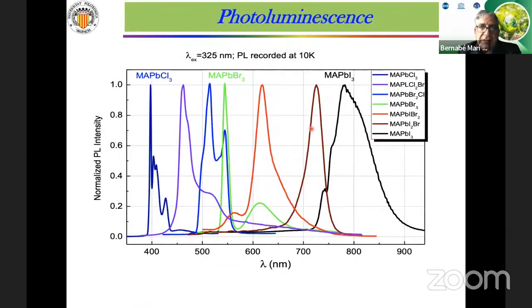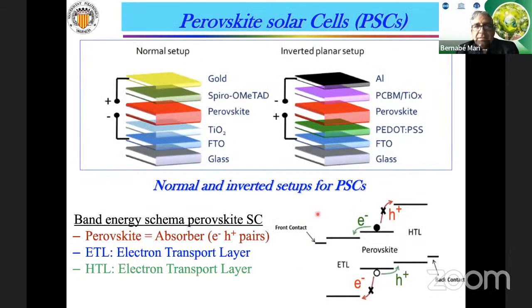Well, this kind of material also exhibits very good photoluminescence, and this slide represents the photoluminescence intensity as a function of wavelength. Again, we have low energy for the methylammonium lead iodide, bromide is in the middle, and chloride is the high energy. And we mix the composition so we can obtain the emission in the range we are interested in. Well, in order to build perovskite solar cells, we have to build several layers.